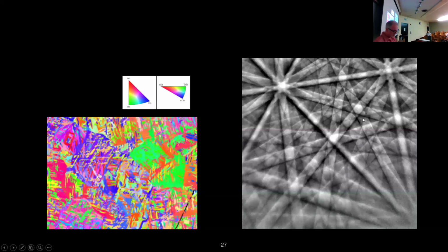And the image to the right is actually a Kikuchi pattern. Kikuchi diffraction is named after this Japanese guy named Kikuchi who came up with this in TEM. And the advent of high-speed computing and fast cameras and being able to digitize things got it into SEM. So now we can do diffraction over very large areas. I know Alex Ruzicka, he does centimeter scale montages, several centimeter scale montages. So you can gain a lot of statistics. When you're inside TEM, you can't really get a lot of statistics out of that because your specimen is typically maybe 6 to 10 square microns.